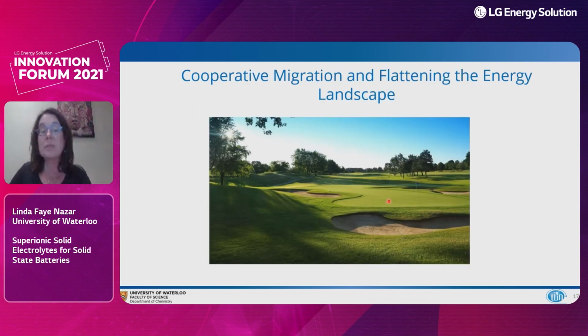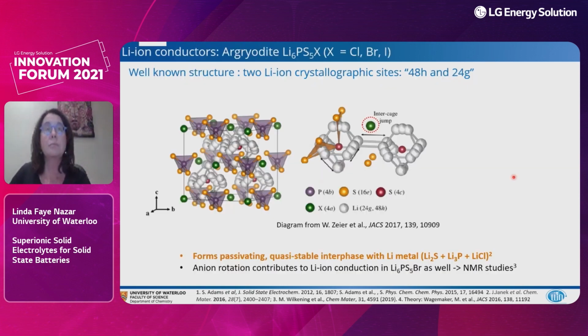So now I'll switch gears and discuss cooperative migration and flattening the energy landscape, this being a picture of a golf course with ideally not very deep sand traps, which is what we're trying to achieve. So one of the most well-known solid-state ion conductors is the materials based on the argyrodite structure, whose formula is shown here. And so X is variable between chlorine, bromine, and iodine. It's really only the chlorine and bromine materials that are the fast ion conductors.